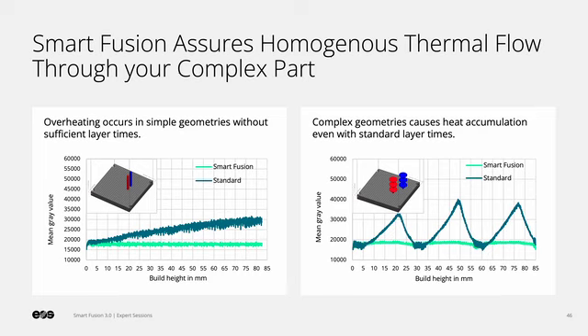The trend in this case is the further away we are from the build plate, which acts as our heatsink, the lower the energy input needs to be. This then leads to a homogeneous mean gray value for the entire part. In the heat demonstrator, the thermal history is a bit more complicated.